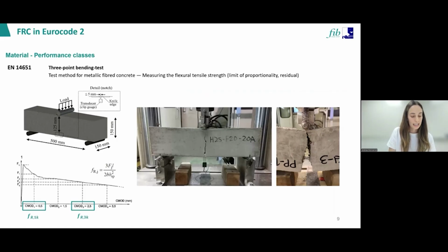So this property, the residual behavior of steel fiber reinforced concrete, is indirectly characterized through the 3-point bending test defined in the EN 14651. The test consists of a notched beam subjected to bending, where the applied load is related to the crack mouth opening displacement, known as CMOD.